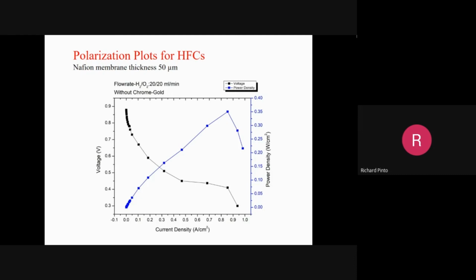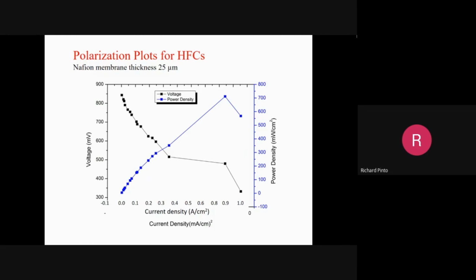Here you see 350 milliwatts. This is power density in watts per centimeter square. So 350 milliwatts per centimeter square is the peak here, with the current density, flow rate and so on. So 20 ml per minute of hydrogen without chrome gold coating. And then this one is